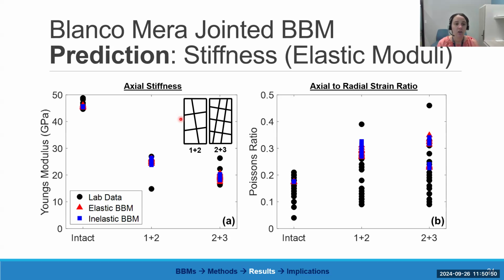So the overall magnitude of stiffness controls the Young's modulus, whereas the ratio between the normal and the shear stiffness values controls the Poisson's ratio. I found that it's easiest to start with Poisson's ratio. So find the correct ratio between normal and shear stiffness, calibrate the Poisson's ratio, and then you can keep the ratio the same but increase and decrease the magnitude of the stiffness values to match your Young's modulus. So that was the starting place for calibration.